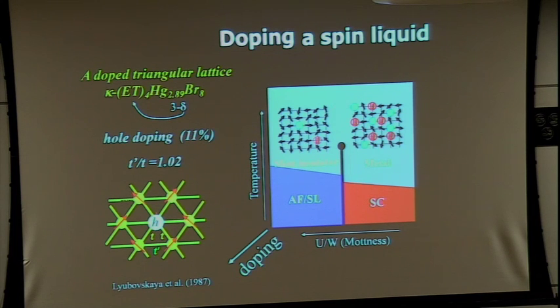Next, doping a spin liquid. Spin liquid we have. Probably we have the spin liquid candidate in organic materials. But organic materials are not good at being doped. Doping is a very effective method in high temperature superconductivity or transition metal oxides, because the transition metal oxides easily accommodate alien atoms with different valence. However, organic materials dislike alien species with different valences. So that is the main reason why doping in organic materials is not successful.